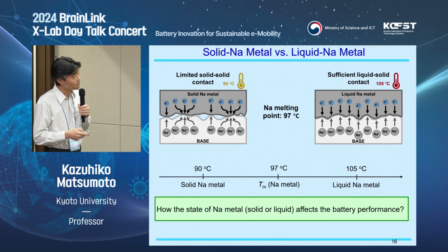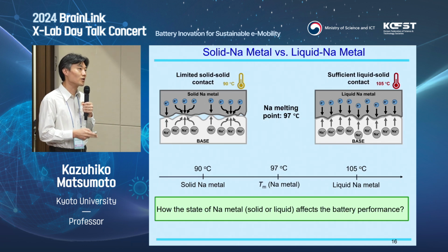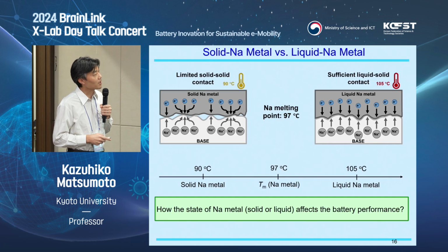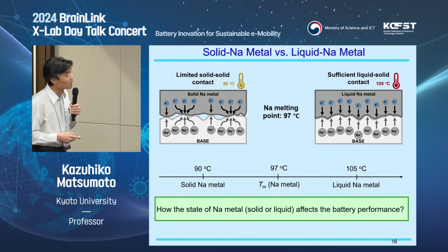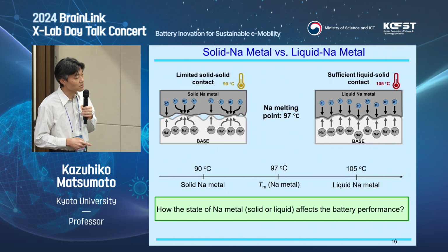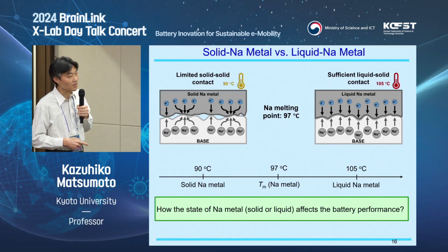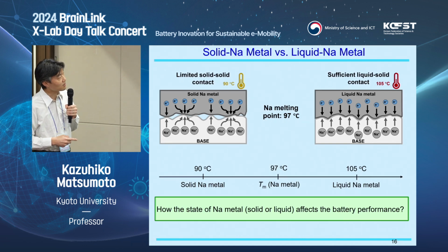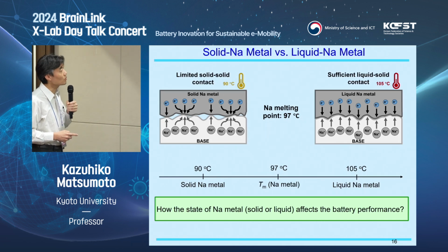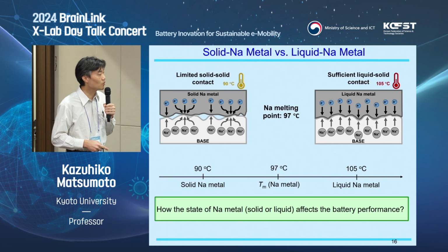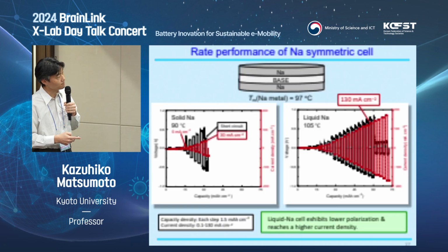deposition behavior. Because we worked at low temperature and also at high temperature, we were wondering what happens at the interface and compare the solid sodium metal and liquid sodium metal on the beta alumina solid electrolyte. Because melting point is 97 degrees C, and if we work at 90 degrees C, it's solid sodium metal. And if we work at 105 degrees C, it's liquid sodium metal. And we expect the bad contact in the case of solid sodium metal and beta alumina, and how the state of sodium metal affects the battery performance.